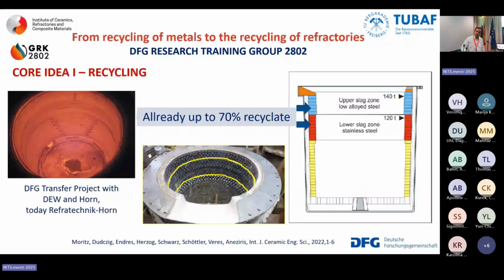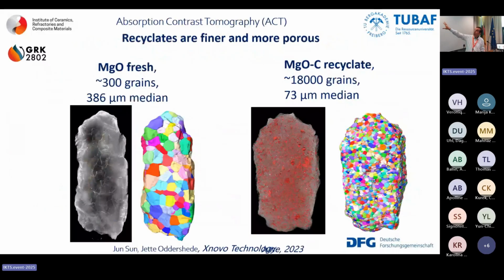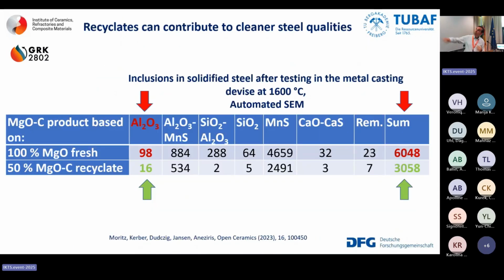Yes, the recycling is something that works, but you always have to pay attention. This is magnesia fresh. This is magnesia recycled. The grains are becoming much smaller. Porosity is increasing. It's contaminated. And the most important, the calcium to silica ratio is also decreasing. You lose calcium. And you need calcium, the calcium silicate phases and so on, in order to meet the demands of creep. But if you go and measure the inclusions in the steel casting simulator, you see, due to the fact that you have a saturated material, you decrease the interactions.